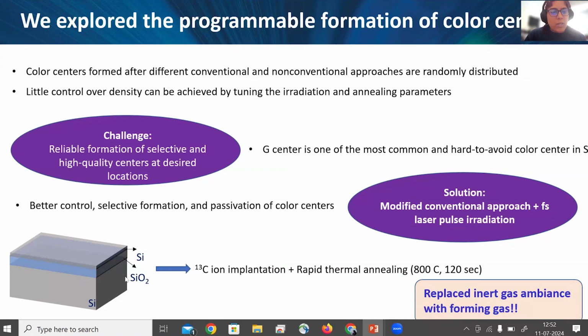So what we essentially do is we start with a silicon on insulator wafer, which is essentially a silicon bulk wafer, and then a few micrometers of silicon dioxide and another few 100 nanometers of silicon on top. The reason why we would like to have this kind of SOI wafer instead of just a silicon wafer is because eventually we would like to integrate our qubits with other photonic components like photonic crystals, waveguides, etc., to realize a full-scale quantum computer.